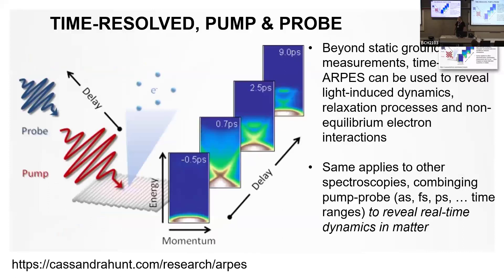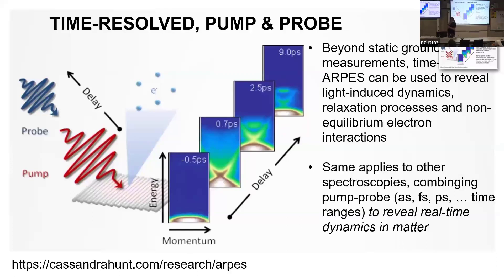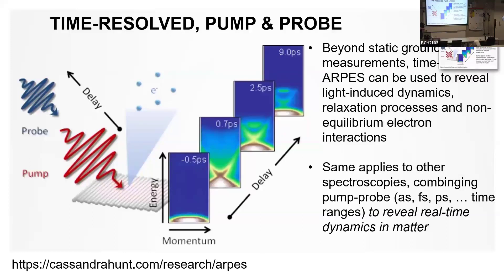An interesting development in this field is going time-resolved. Very useful is to do pump-and-probe experiments: an external pump — maybe a laser pulse — excites the system out of the ground state, and then you probe that excited state, looking at the dynamics in real time as the system decays. This brings very interesting information on light-induced dynamics, relaxation processes, and different kinds of non-equilibrium phenomena in matter, allowing us to tune material properties by bringing matter to an excited state. This is a very active field, combining pump-and-probe on femtosecond or picosecond timescales to reveal real-time dynamics.